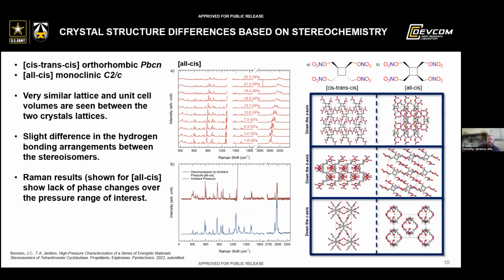So here's some work that we did using Raman spectroscopy on this page. First of all, you can see the cis-trans-cis and the all-cis structures on the right there. And then looking down the different axes, you can see they have very similar packing arrangements. In fact, their packing densities are very close. Their bonding interactions are very close. They have a little bit of hydrogen bonding going on, which helps to stabilize these structures.